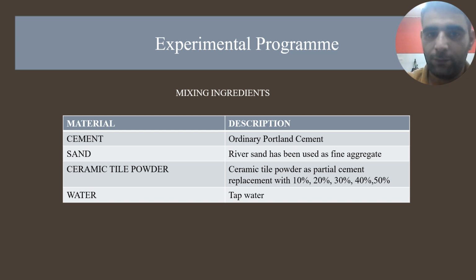Now, experimental program. Here we show the mixing ingredients. First of all, cement. We use ordinary Portland cement for our research. Second, the sand. River sand has been used as a fine aggregate. Ceramic tile powder as a partial cement replacement with 10, 20, 30, 40 up to 50% replacement of cement. At the end, the water. Tap water, clean water, was used in this study.